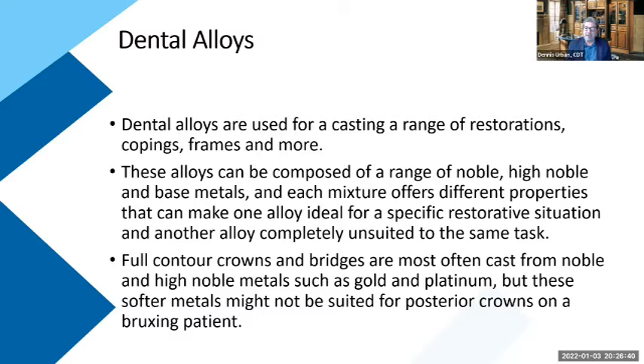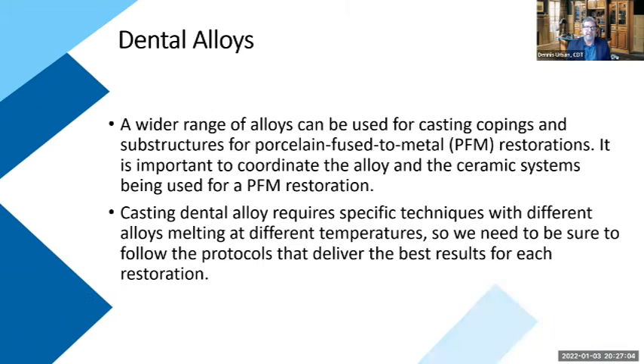And they can be composed of a range of noble, high noble, and base metals, and each mixture offers different properties that can make one alloy ideal for a specific restoration over another alloy. Full contour crowns and bridges are most often cast from noble and high noble metals, such as gold, platinum and palladium. The softer metals might not be suited for posterior crowns on a bruxing patient, like I mentioned earlier. So we have a range of alloys that can be used.